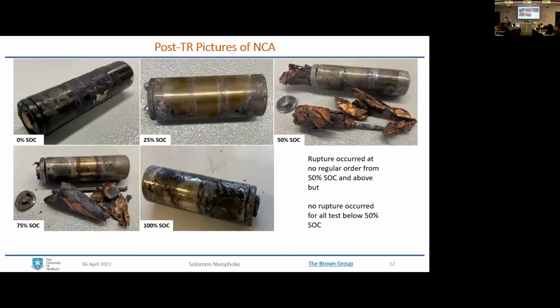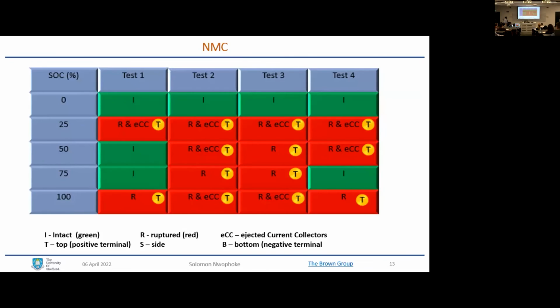Then these are the pictures of the battery after the test. You can see here, at 0 state of charge, the battery remained intact. It just released some droplets of melted current collector, which is aluminum. Then this one ruptured and ejected content, and this one ejected content as well, but 100 is still intact. So it is not very clear what really influences this rupture or being intact, because if this can happen at 50 and 100 is intact, I can't really explain what happened there. So rupture occurred in no regular order from 50 state of charge and above, but no rupture occurred in any tests below 50.